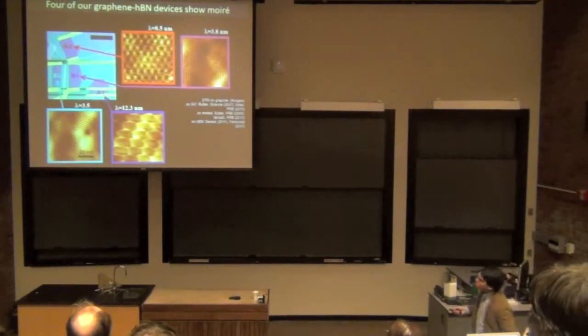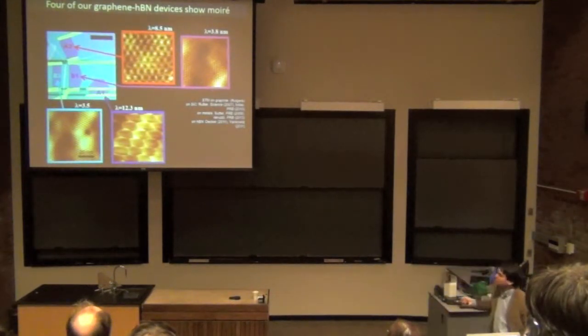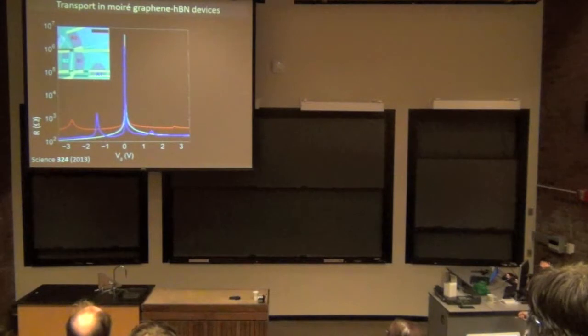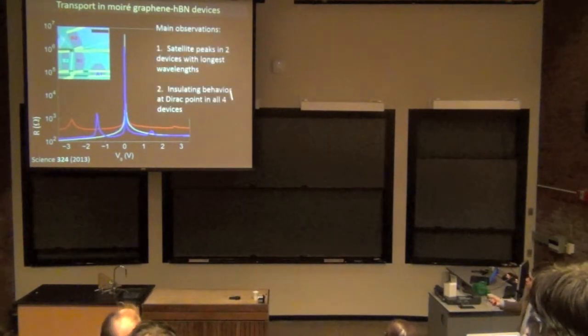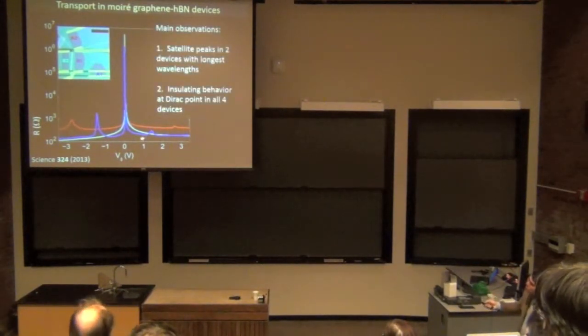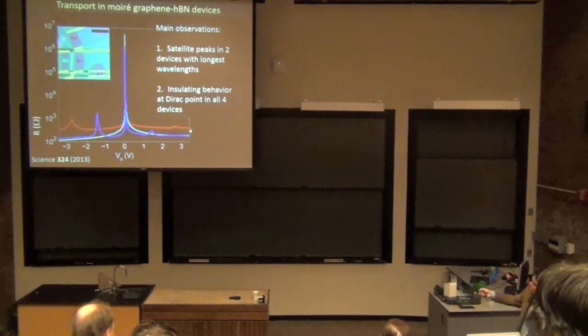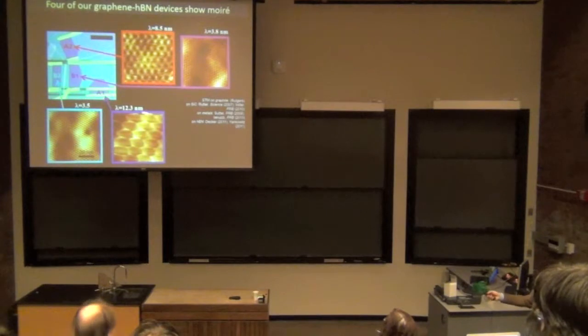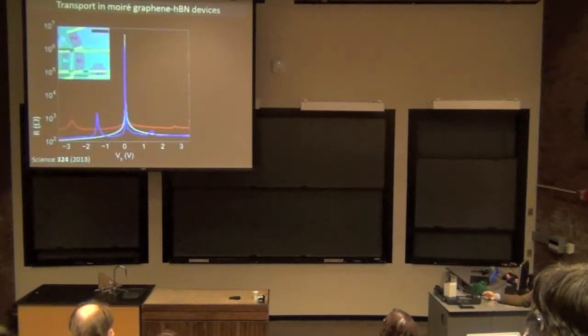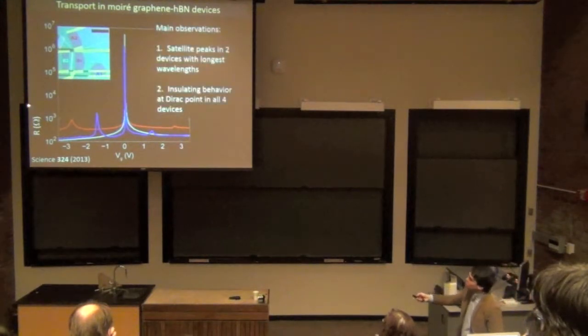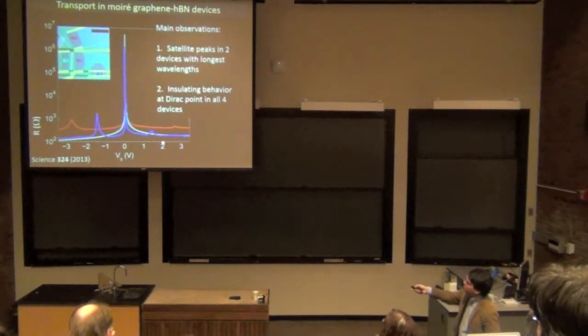And the transport characteristics of these devices are very different from what you saw before. In fact, there are two additional features that I want you to see. One is that there are these additional satellite peaks in the two devices, the red and blue, with the longest moiré wavelengths. So again, just go back. Here's one moiré wavelength at 12.3 nanometers, one at 9 nanometers. And in those two devices, we see these additional peaks on the side.